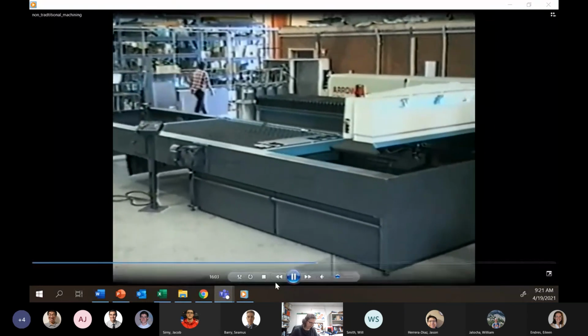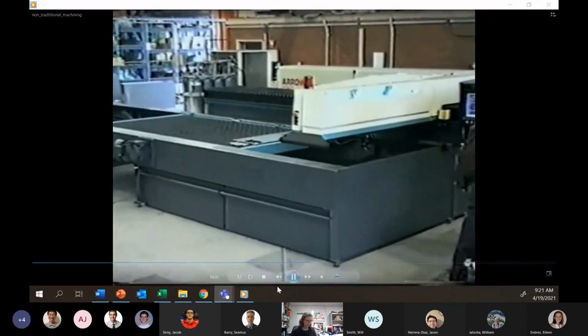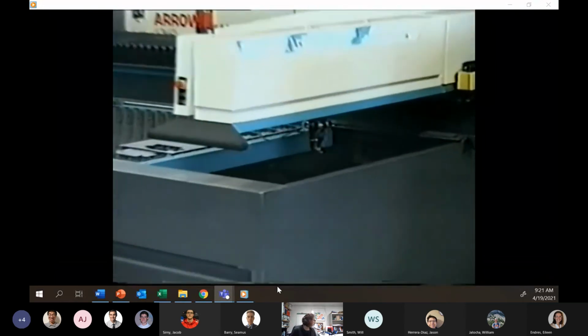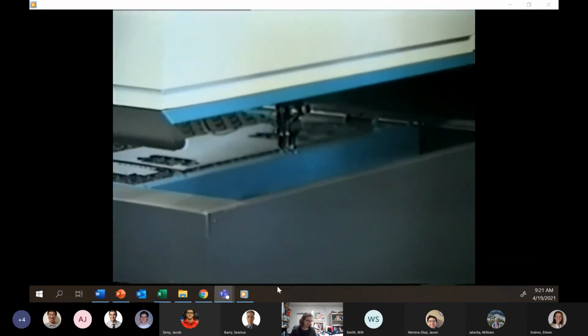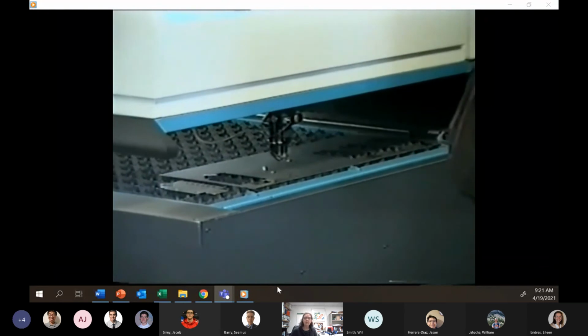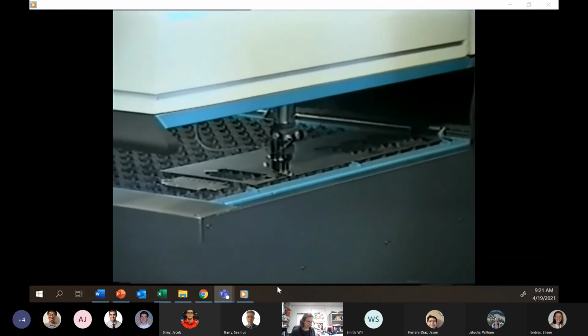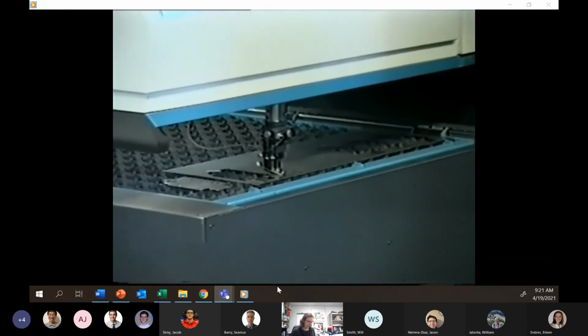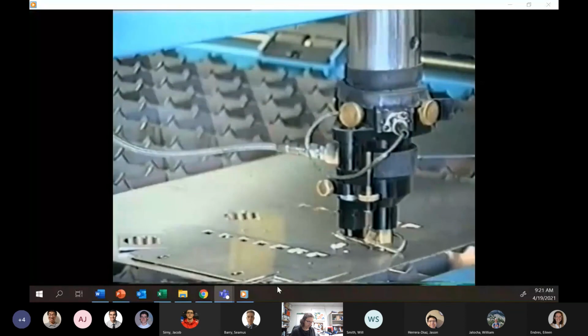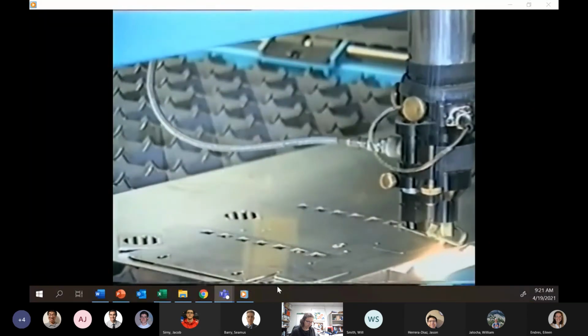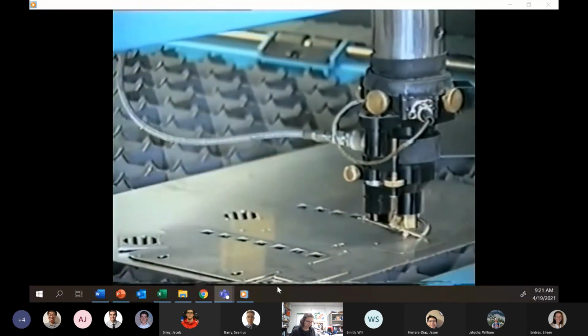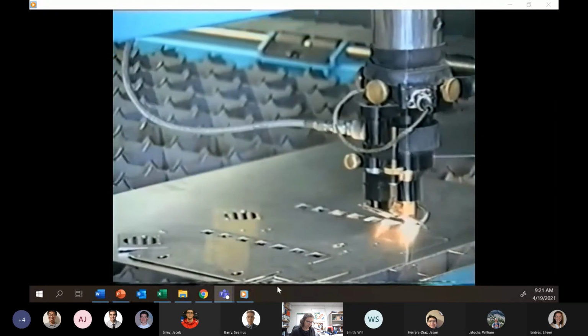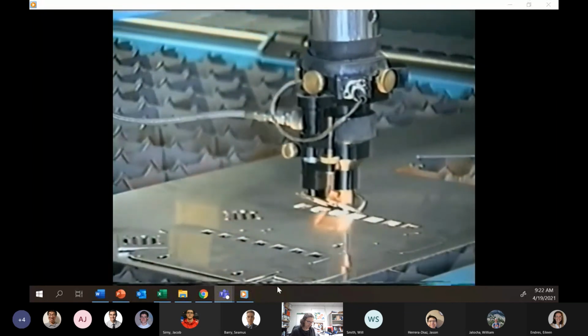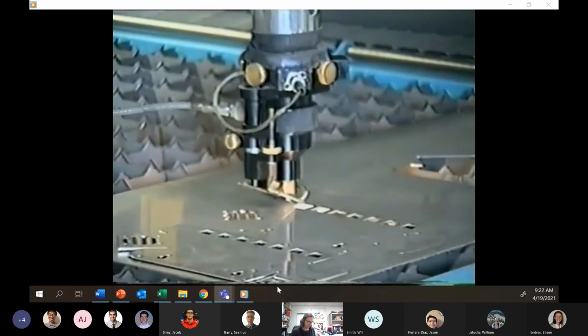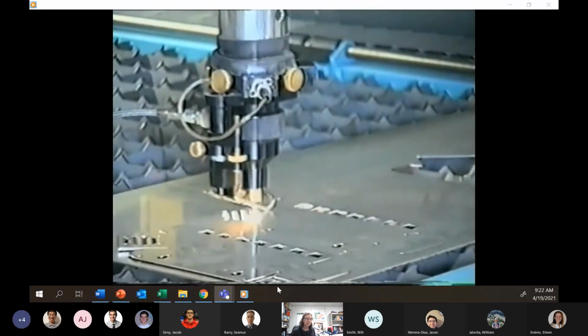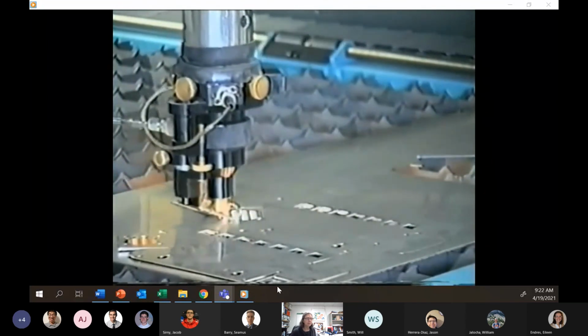The Laser Lab profile machine has two tables, 3 meters by 1.5 meters, that pass under and over each other, allowing one table to be unloaded and then reloaded, while material is being cut on the other table, giving an improvement in machine productivity of up to 50%. With 2,500 kilopascals of high-pressure nitrogen, clean cut, tolerances of plus or minus 0.1 of a millimeter can easily be maintained over the shape.